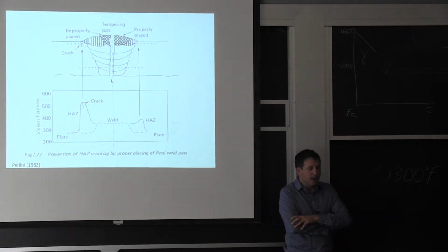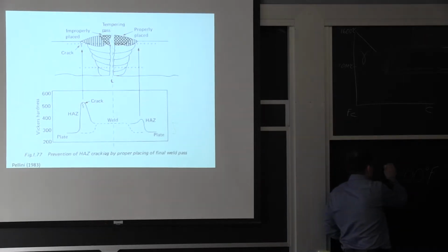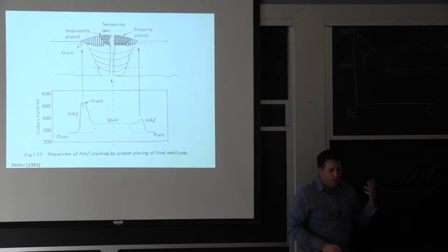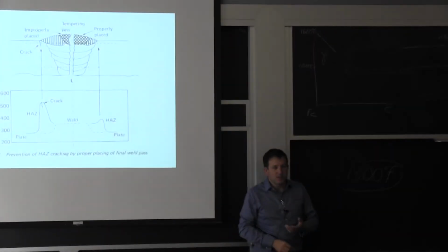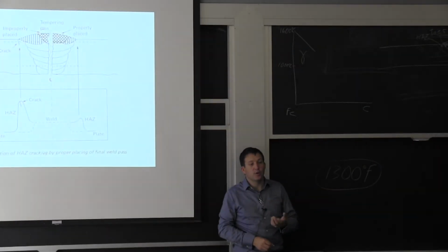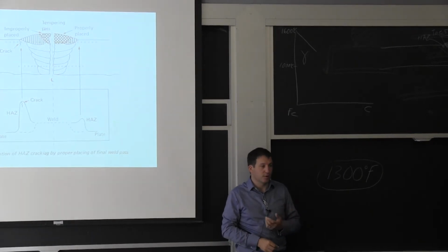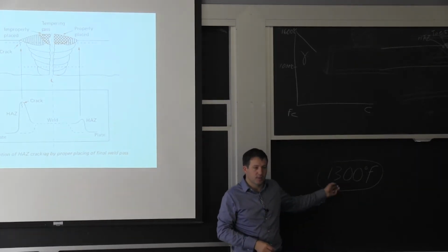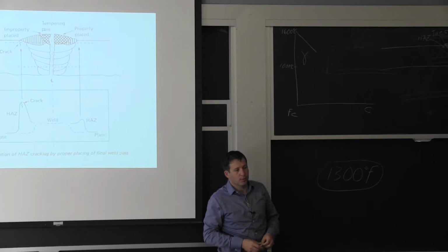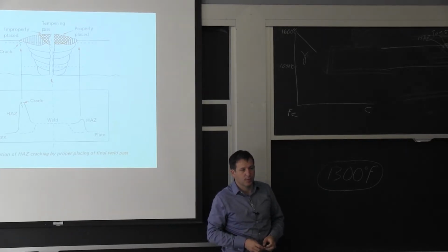The reason I'm mentioning this about the stress relief is we try for the stress relief to not lose anything we've developed in the steel in terms of strength. So we don't want to go back to austenite if all we're looking for is a stress relief. And that's why typically we go to a lower temperature and we hold it for a sustained period of time.